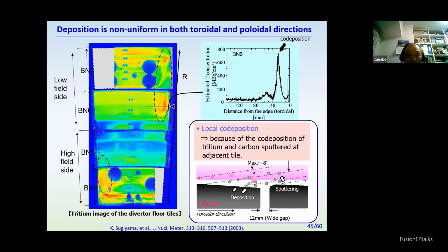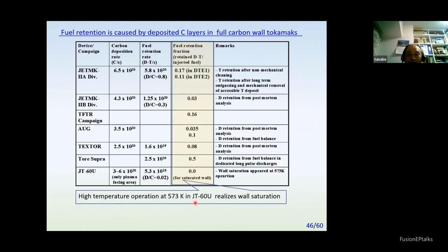So in carbon cases, deposition retains a lot of hydrogen. Correspondingly, fuel retention rate in carbon machines is very large. In case of Tore Supra, operated at room temperature, it's very high, 50%. But at high temperature operation, for instance in Textor, it's 8%. If you go to higher temperatures, all are saturated. So the retention rate depends quite a lot on the temperature of operation.